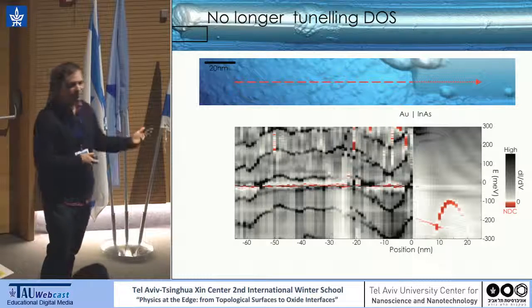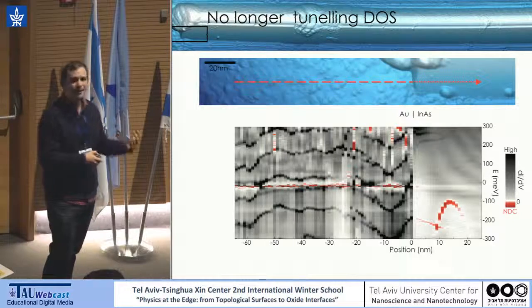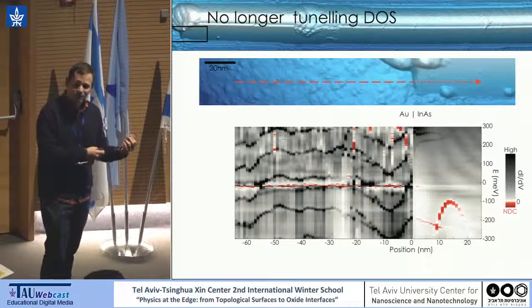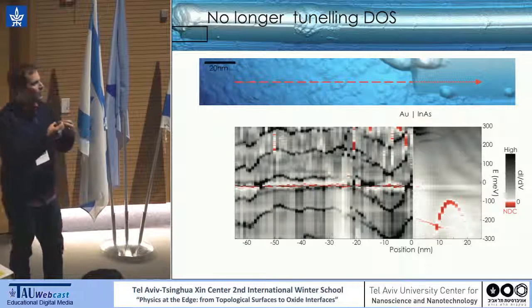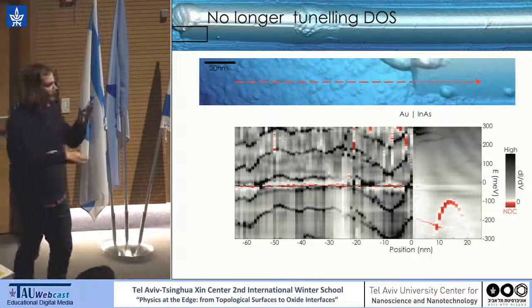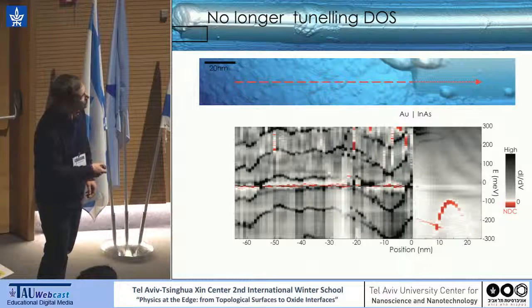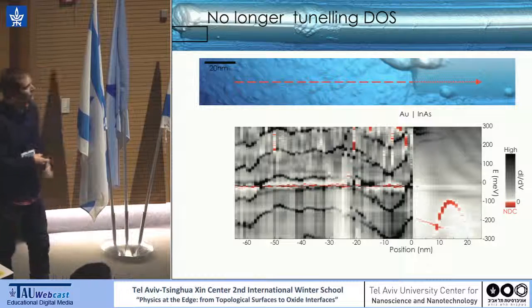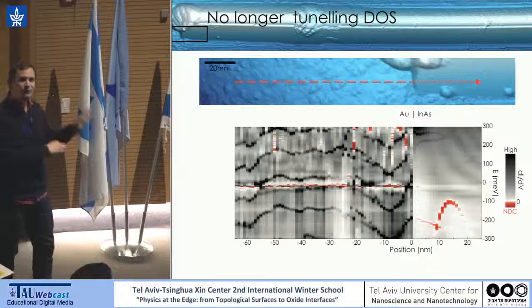The spectrum inside the gold ball is highly quantized, which means that this gold ball is very dirty with indium and arsenic, and is made of lots of tiny quantum dots which are coupled to each other. And this gives rise to these very large gaps in the quantized spectrum, and to the fact that the resonances meander in energy. So this is one quantum dot, and this is a second one, and this is the transition. You see here the forking of the behavior, and the tip is not very happy when you go across them. So the gold ball is heavily quantized.